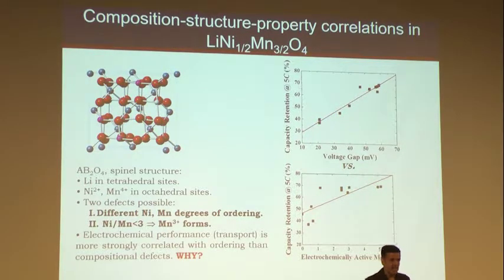The other kind of defect that you can have with this material is that it tends to have an understoichiometry of nickel. If you count electrons in this composition, you'll conclude that this must be nickel 2 and manganese 4, and that's what they are. But manganese has this habit of reducing somewhat with temperature, and these are made at high temperature. So you end up with a little bit of manganese 3 and a little less nickel in the structure to compensate. They're slightly nickel deficient when you make them. It's very common; it's very difficult to get stoichiometric materials. So you have these two types of defects.